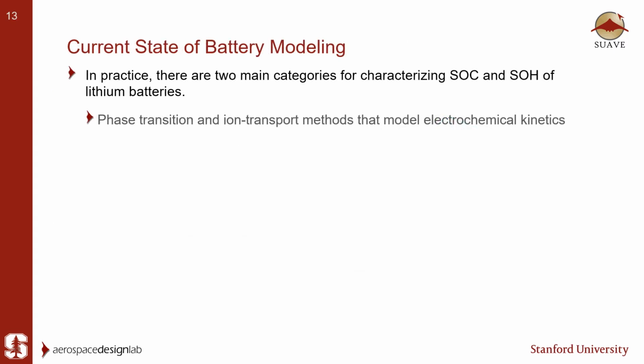Now in practice, there are two main categories for characterizing the state of charge and the state of health of a lithium battery. State of charge is essentially how much energy a battery has in one particular cycle, and the state of health can be thought of as the state of the battery after X amount of cycles. Essentially, how well the battery performed at day 1 as opposed to day 100. The first method is a phase transition and an ion transport method that models electrochemical kinetics. However, this model is very computationally expensive and is not really suited for real-time applications.